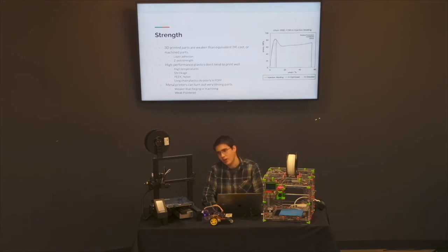Or even a more common option would be nylon. Most people don't think of nylon when they think of a super high performance plastic, but it's pretty strong. And it's really quite a pain to 3D print. A lot of this has to do with the fact that high performance plastics print at higher temperatures. And the higher temperature you get, the more prone your parts get to warpage, because one section of the part is going to be considerably hotter than another and thus expanded.